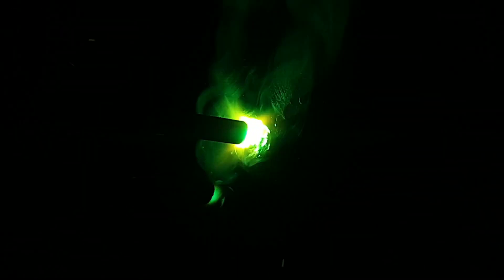The reason why it's so important that we hit 50% of the previous run is to make sure we've got a flat surface and we don't leave any material that can catch slag traps. If you can imagine, if we've got gaps in between our weld it's not going to look very professional. Not only that, we've got weak points in all parts of the weld everywhere there's a gap, so we need a nice consistent base, a nice flat base all the way over the capping run. Same process: make sure we deslag, grind that little gully into it so you can join up your next run, make sure you maintain that arc angle keeping it nice consistent and straight throughout. If you've done it correctly it should be overlapping and look like this.